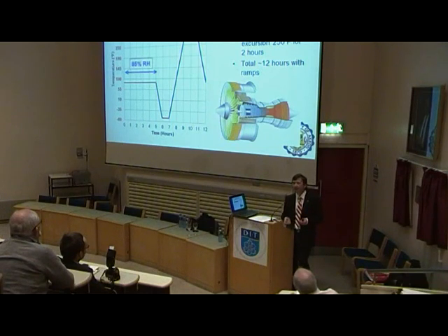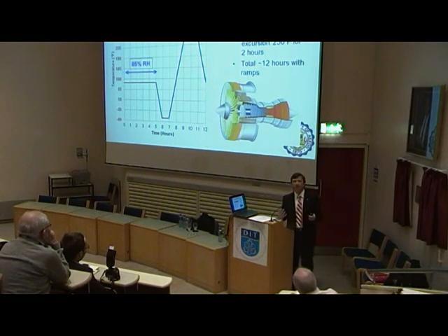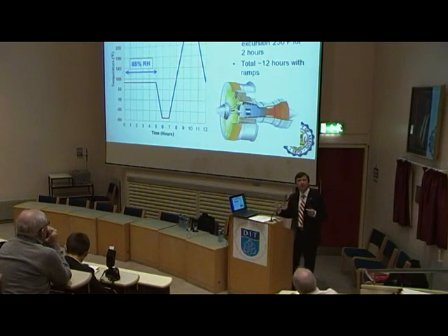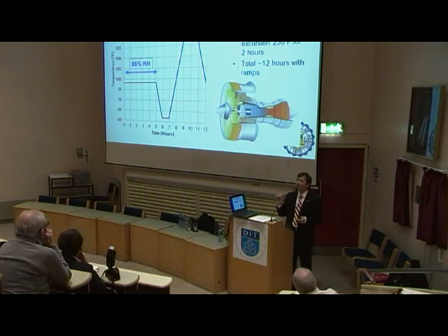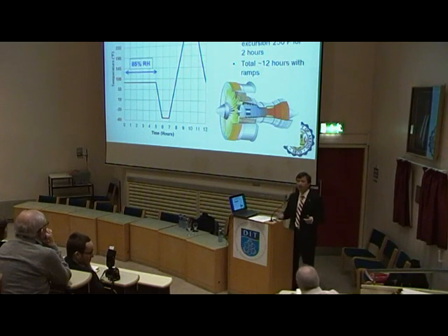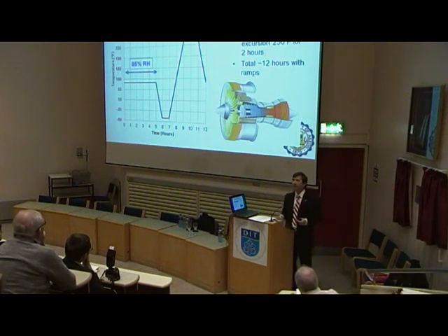All these conditions and the application of different gases can deteriorate the material behavior. So we were asked to use our laboratory, and we have a special environmental chamber where we submitted this material to the aging process, and we tested again after months, 2 months, 1 year, 2 years, 3 years, 4 years, and found out if this material is going to behave properly at the end of life. Because for designers, it's easy to get the properties of the material when it is produced. You can go to the laboratory and test just after fabrication.